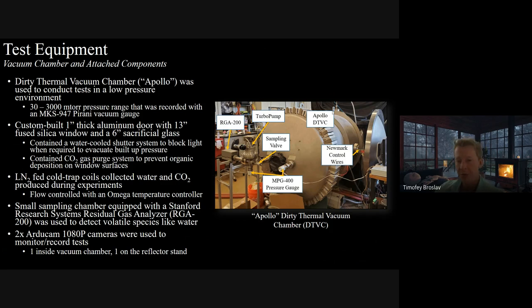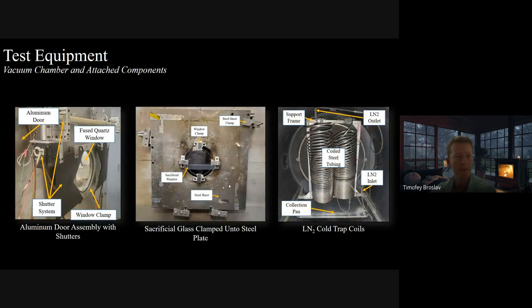Liquid nitrogen cold traps were housed in the back of the chamber. I mentioned those a little bit earlier. More so, a residual gas analyzer, RGA 200, was used to detect volatile species, mainly water, during testing. Lastly, 2 cameras were used. One was inside of the chamber to obtain video feed of the test, and one was outside, positioned right underneath the reflector, just to make sure that things were operating nominally during testing.